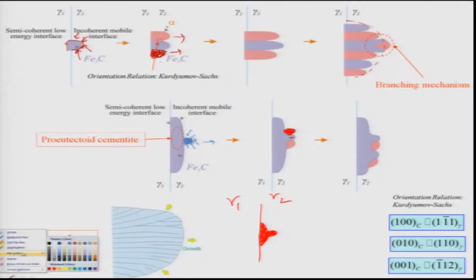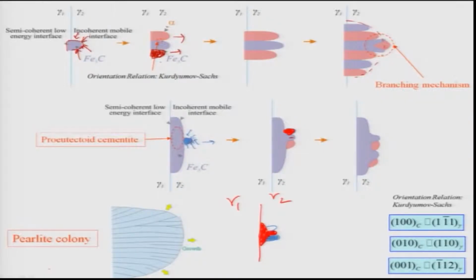And because the growth of alpha requires very little or actually no carbon, the nearby regions will become very rich in carbon. When the carbon concentration reaches the critical concentration required for nucleation, Fe3C will nucleate on both sides, and finally it will lead to formation of a colony. This colony has the pro-eutectoid alpha as a nucleating site, not the gamma grain boundary, and this will be followed by formation of these colonies. These colonies will again look the same as a pearlite.